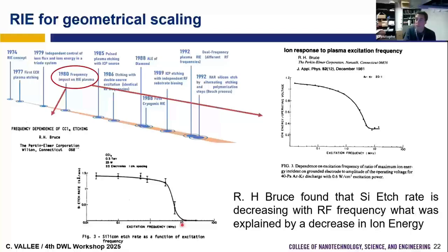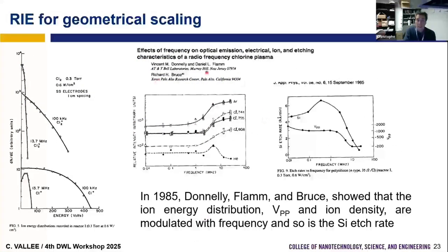He observed a huge drop of the etching rate, and the drop was explained by the fact that the energy of the ions is decreasing. So he observed that when we go to very high frequency, we decrease the energy of the ions. In addition, with Flamm, for example, Donnelly also did a lot of papers to try to understand the impact of generator frequency on the plasma properties for the etching. What they found is that if you increase the frequency of the generator, you increase the plasma density, so high frequency gives a dense plasma. But if you increase the generator frequency, you decrease the peak-to-peak voltage. So at the same time, you decrease the ion energy, and so you decrease the etching rate, as was observed by Bruce.